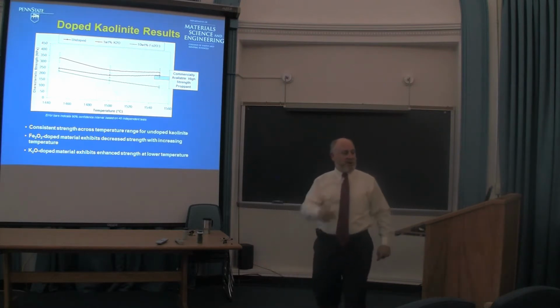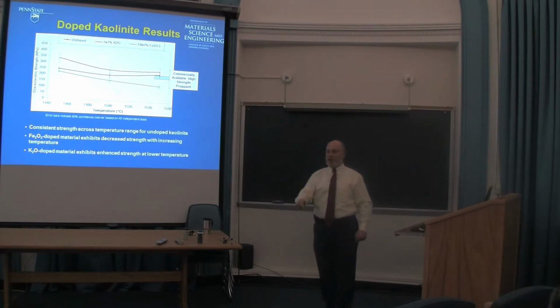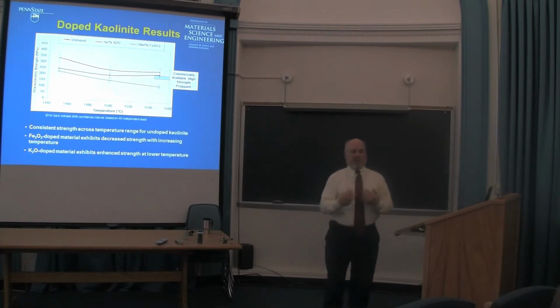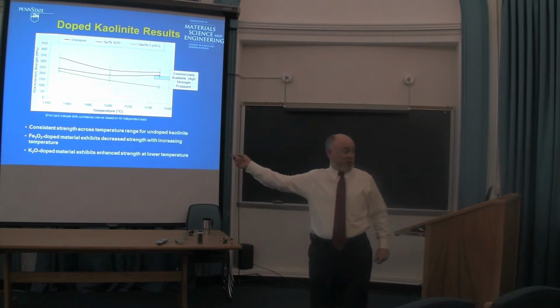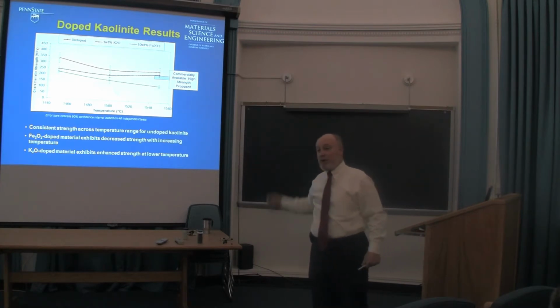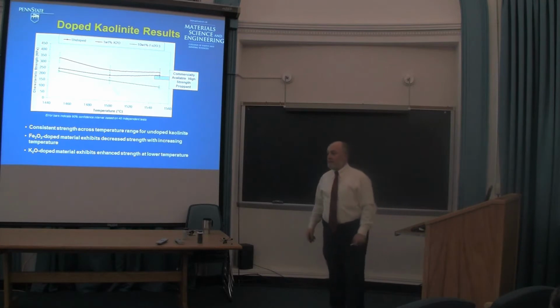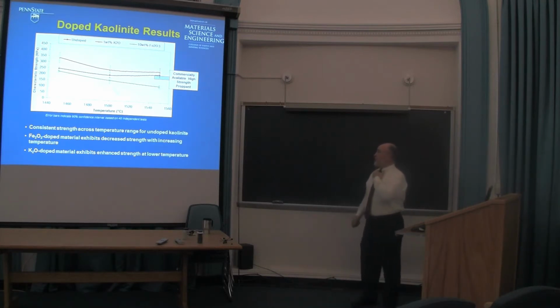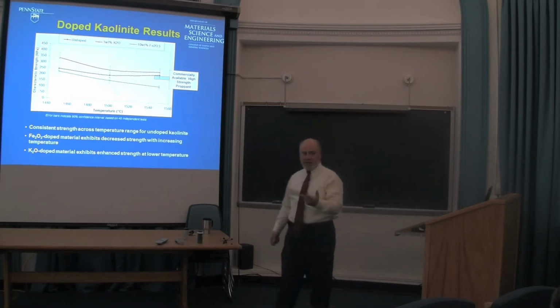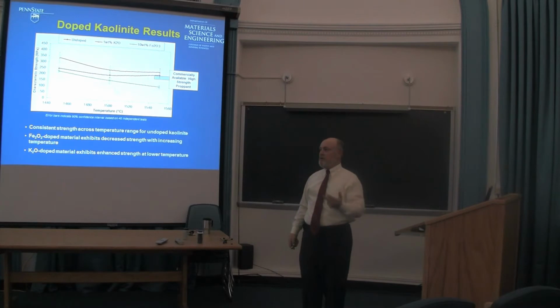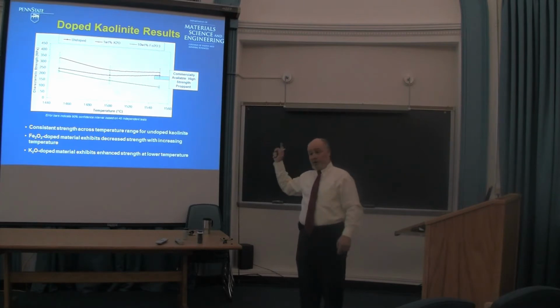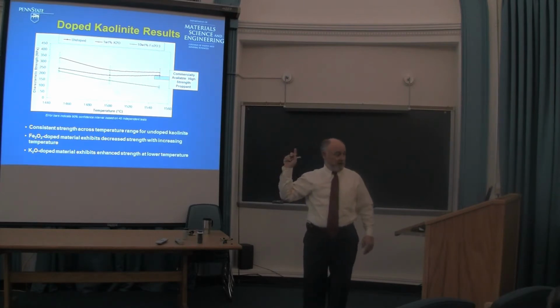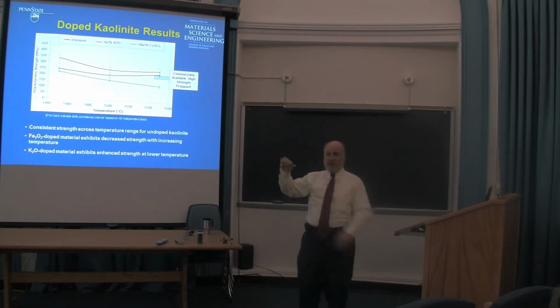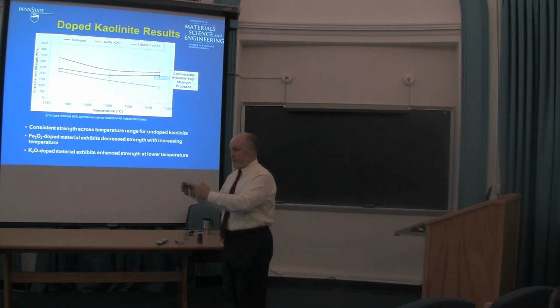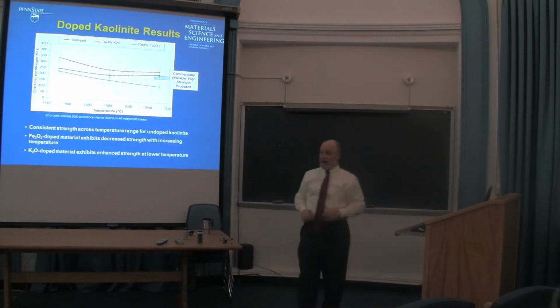So what we told them was deliberately add impurities. Deliberately add dopants. So we can see what effect it has so that you can go out and you can buy chromium ore as your raw material to make a better product. Okay. So the end result was, if we know something about thermodynamics, if we know something about kinetics, if we know something about the role of microstructural evolution on strength, we can tailor virtually any material to behave and give us a good proppant. The work of sintered bauxites and kaolins, drill cuttings are going to be the same way,